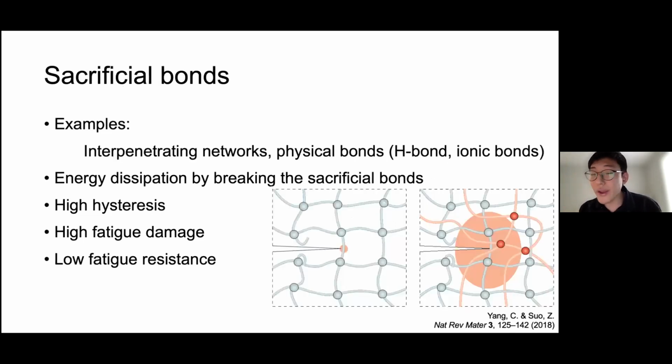There is another way to increase the stiffness and toughness altogether. That is interpenetrating networks, which have been extensively studied in recent decades. The principle is very similar to the fillers, though. You apply secondary and tertiary networks in addition to the major primary network, so that these additional networks break instead of the primary chain and dissipate additional energy as a result of the stretching.